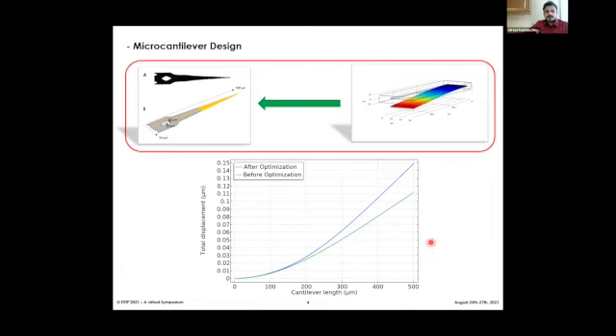Oh, yes. So the chamber is 2 millimeters by 2 millimeters with a height of 100, according to what we needed for our organ chips. We did it with a MATLAB code optimization with a SIMP method with a factor of 3 to reduce 40% of the structure material, polyimide in this case, to have better flexibility. So we didn't test how much improvement for the quality factor, but for the deflection, as per the conducted fluid structure analysis, we have a 36% improvement in the deflection.